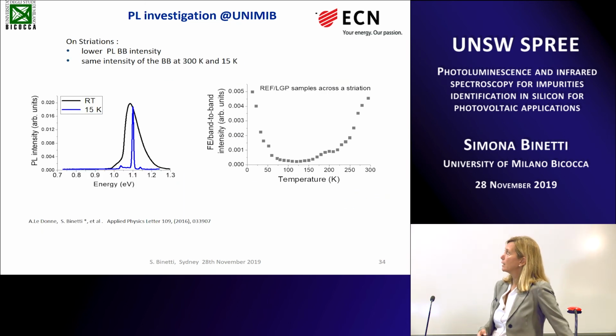And what we have seen was, first of all, a strange behavior of the band-to-band emission and also the free exciton emissions, because as you can see here, the intensity was the same at room temperature and low temperature, and this is not the common situation.